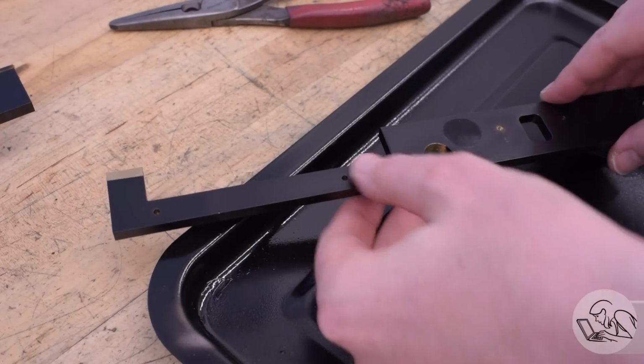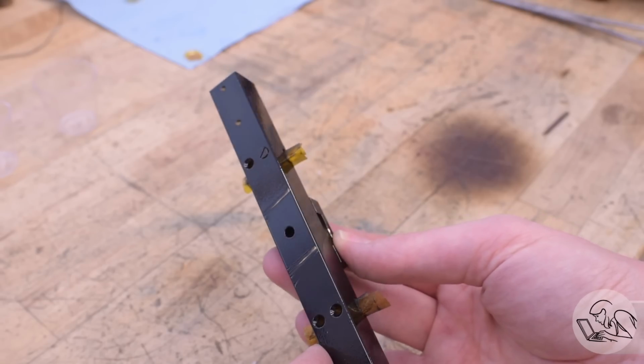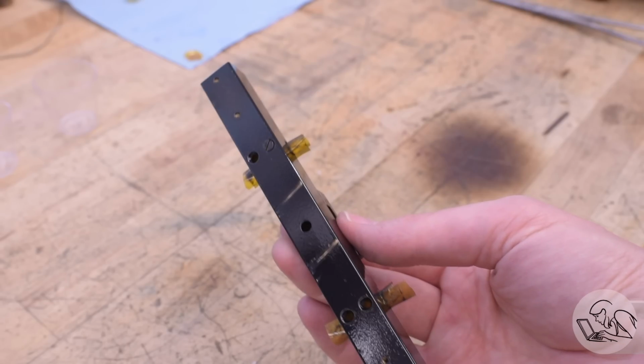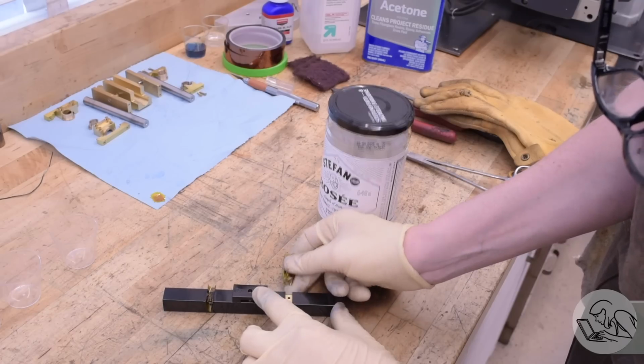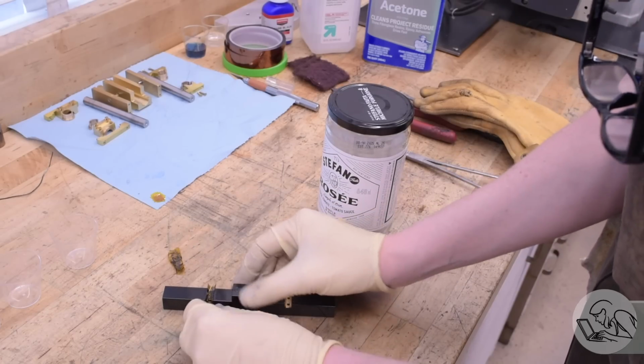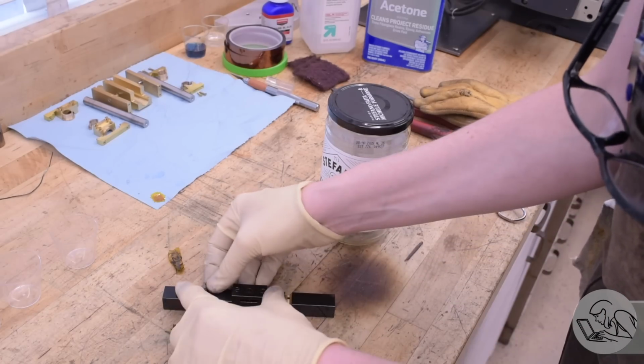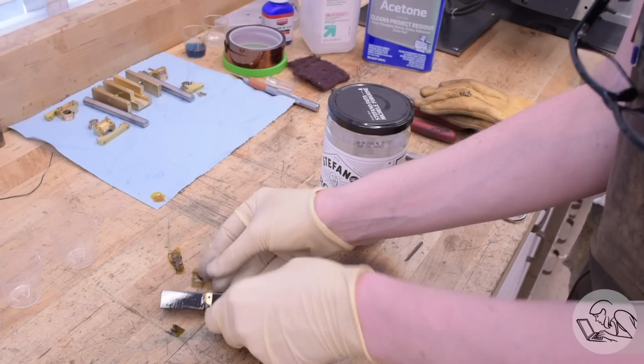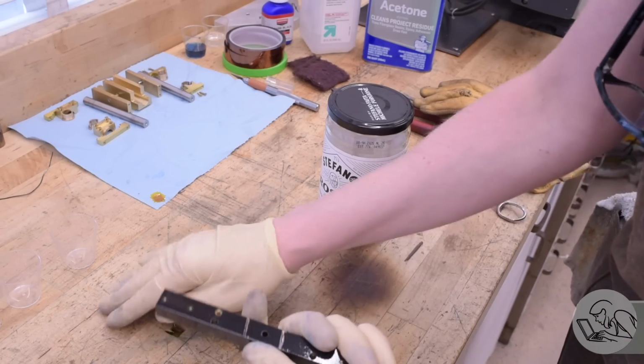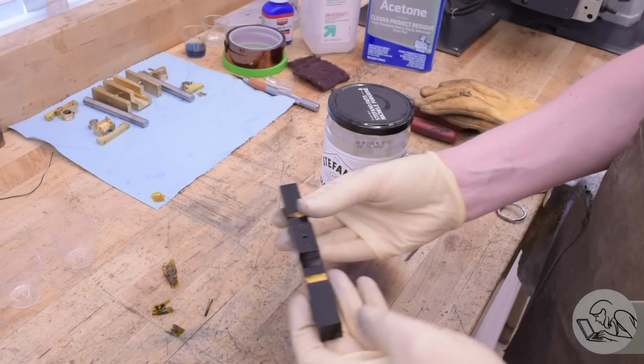I did have one casualty. The rear bolster fell while it was in the oven. My hook wasn't strong enough. This is quite a heavy piece, and the hook gave out, it fell, it landed on the oven rack below and left those barbecue marks. And that surface is going to be facing upwards at the back of the cab, right where you can see it for all time. So I couldn't let that one go. This was going to have to be fixed.